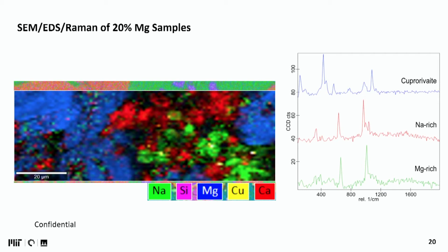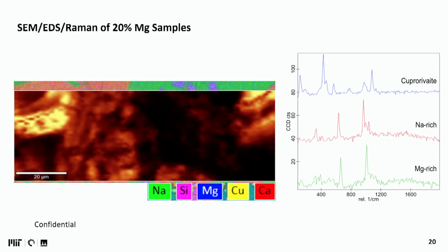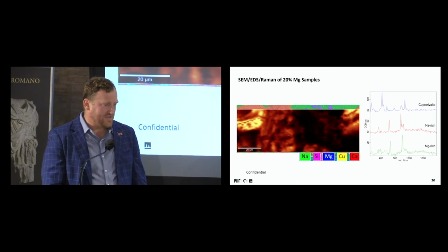And here we show some results that we are hoping to publish soon, where you see magnesium is expelled from the Egyptian blue crystallizing in the mix. This can be easily seen because there are sodium and magnesium rich regions that do not emit luminescence and therefore do not present this amazing structure that we have seen from presentations and in the video. So this is really an important step forward in differentiating what happens during this process.